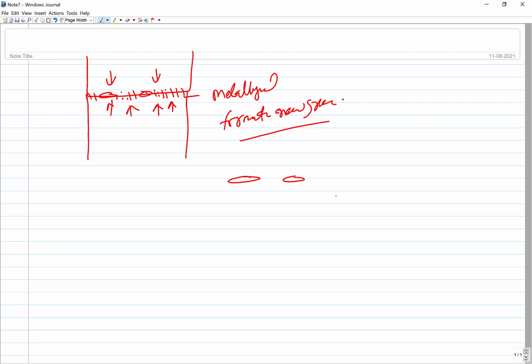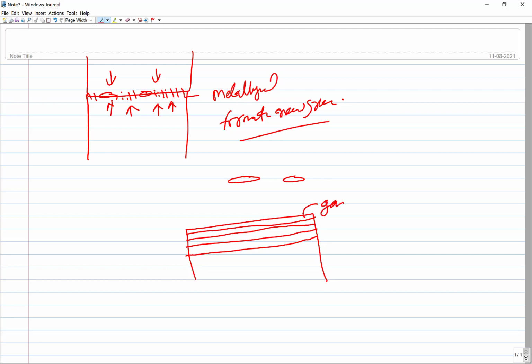These air pockets must be eliminated, one, because atoms cannot move through air. And all surfaces, if you see the surface engineering, are made of 4 or 5 layers like this, and in these layers you will find some dissolved gases, then there are oxides and nitrides present, then there is some kind of deformed layer coming from the machined surfaces, and then the undeformed zone. There are a number of layers. So atoms will have to cross all these barriers.